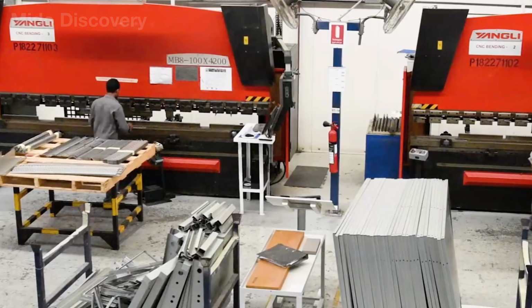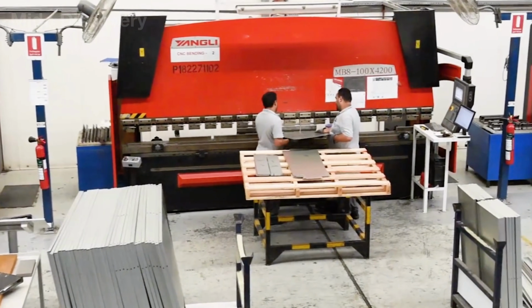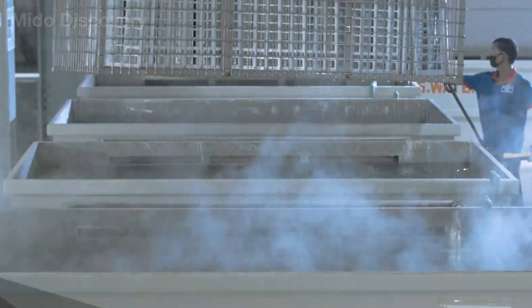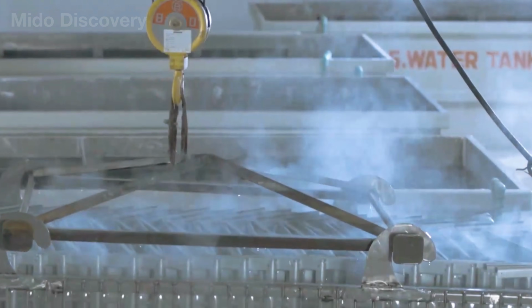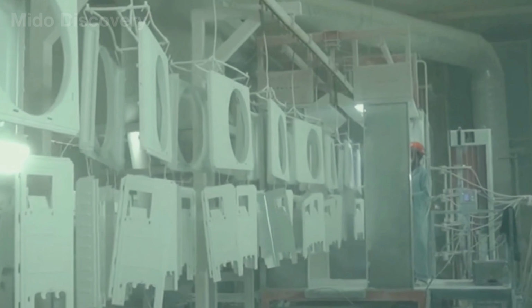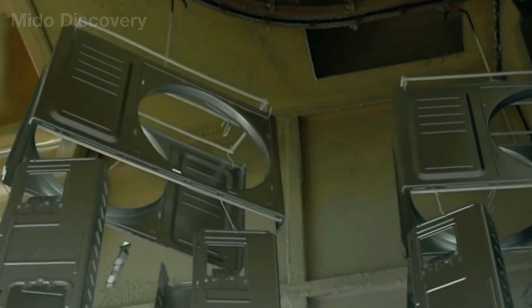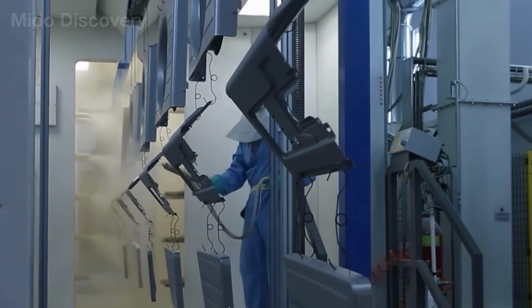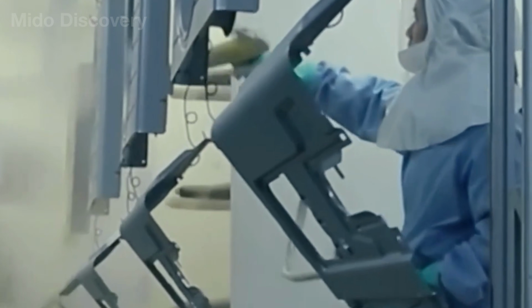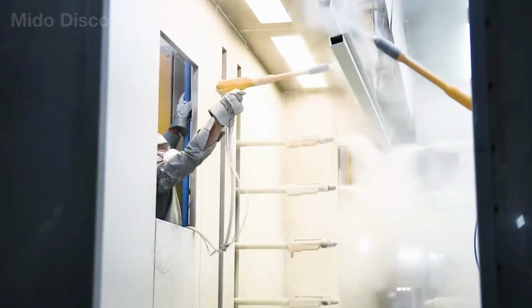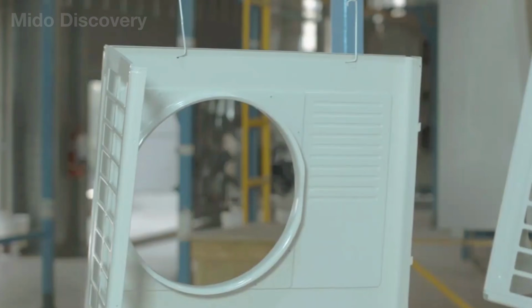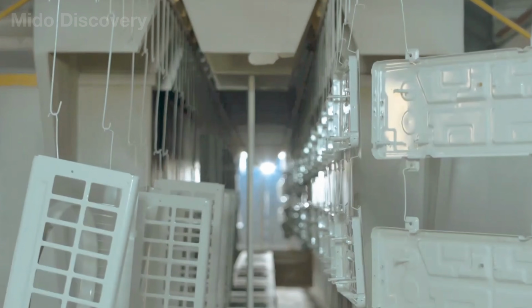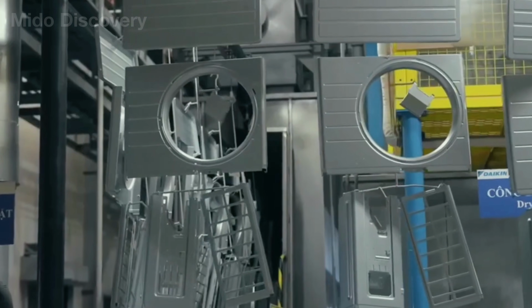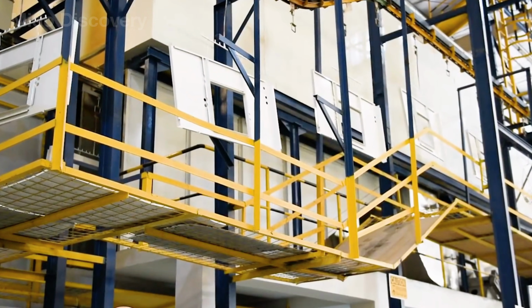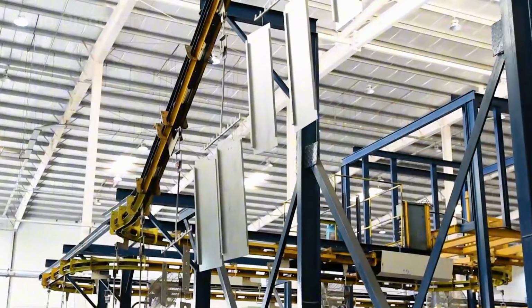After being formed, the metal components are degreased, thoroughly washed, and surface treated to remove dust, oil, and other contaminants that could cause the coating to peel away. They are then suspended from an overhead conveyor and carried one by one into the powder coating booth. Inside, spray guns apply an electrical charge to millions of ultrafine powder particles. The oppositely charged metal draws the powder evenly across flat surfaces, bent edges, and narrow corners that liquid paint may struggle to reach. The coated components then pass through a curing oven heated to approximately 350 to 400 degrees Fahrenheit. At this temperature, the powder melts, bonds to the metal, and forms a hard, uniform protective film.